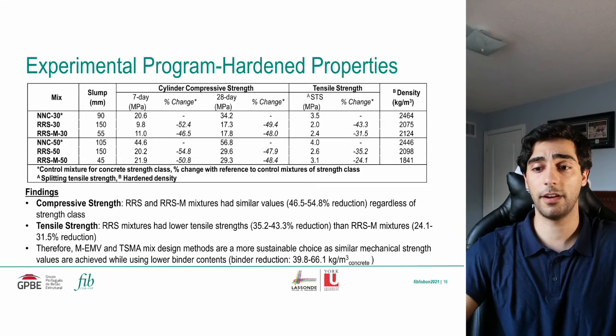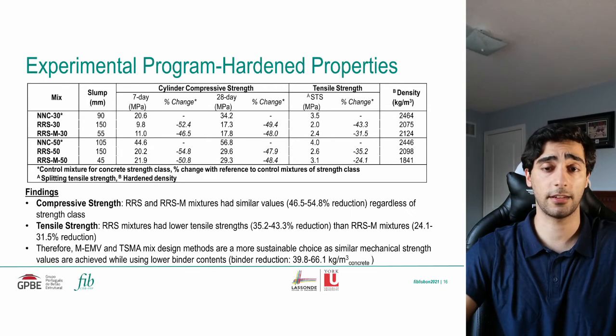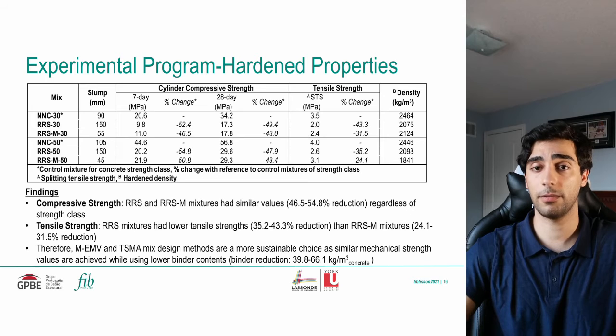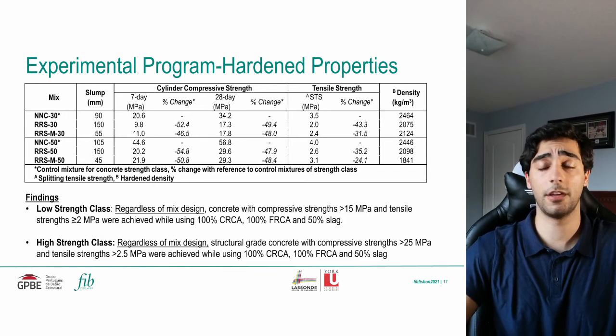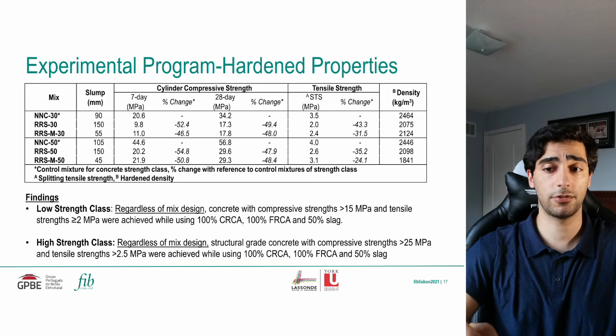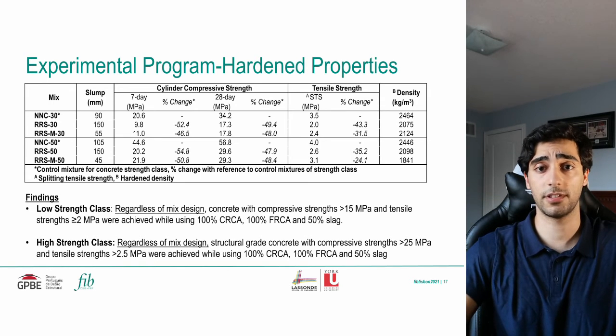Based on the results, it can be found that the use of the modified EMV and two-stage mixing approach led to a more sustainable choice, as they achieved similar mechanical strength properties as the conventional mix design methods, even improving the tensile strength values, while reducing the binder content with a maximum binder reduction of 66.1 kilograms per cubic meter of concrete.